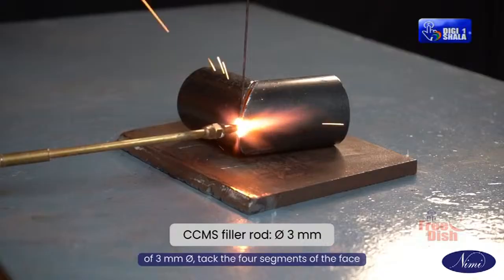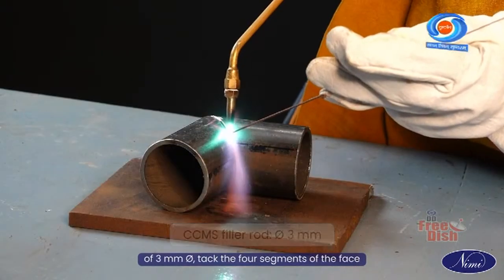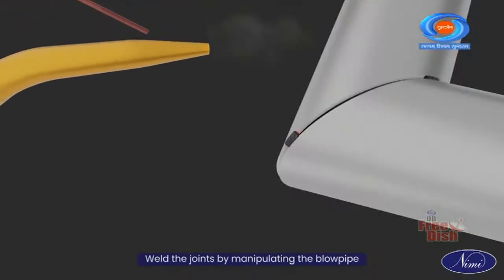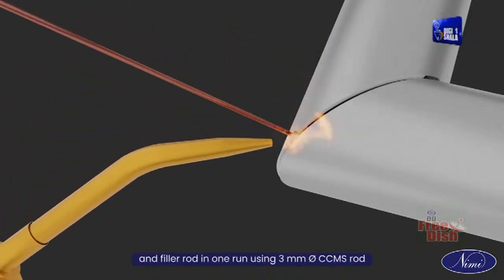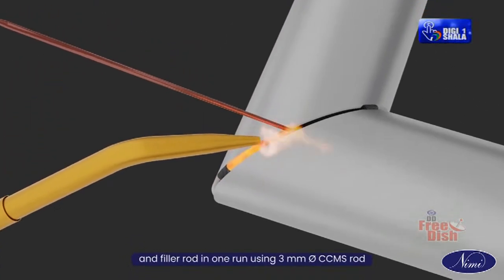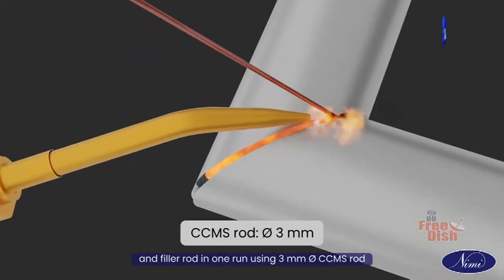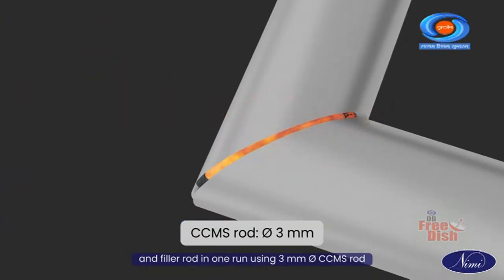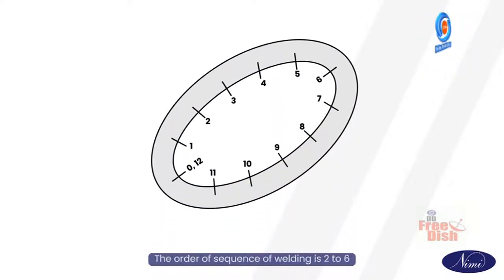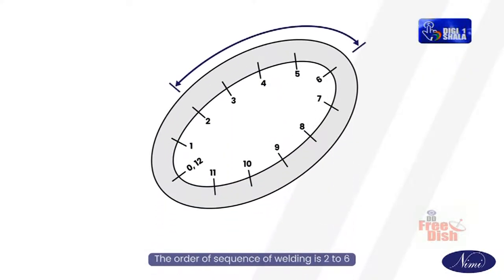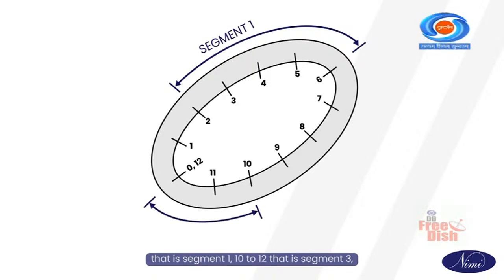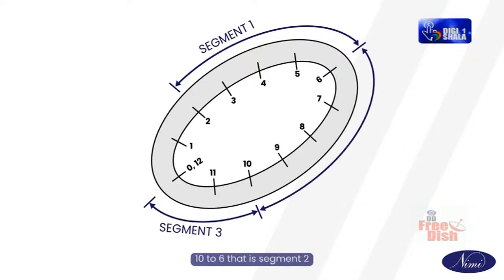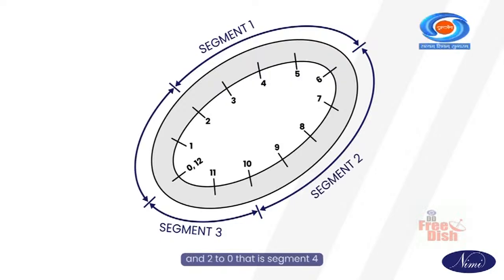Tack the 4 segments of the face. Weld the joints by manipulating the blowpipe and filler rod in one run using a 3 mm diameter CCMS rod. The order of sequence of welding is 2 to 6, that is segment 1, 10 to 12, that is segment 3, 6 to 10, that is segment 2, and 2 to 0, that is segment 4.